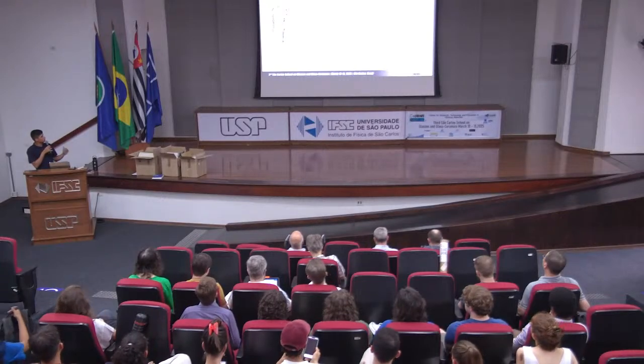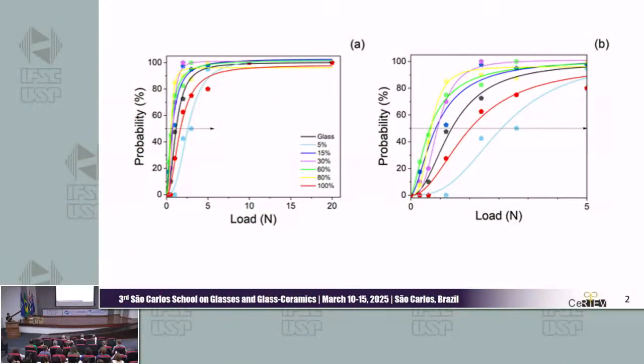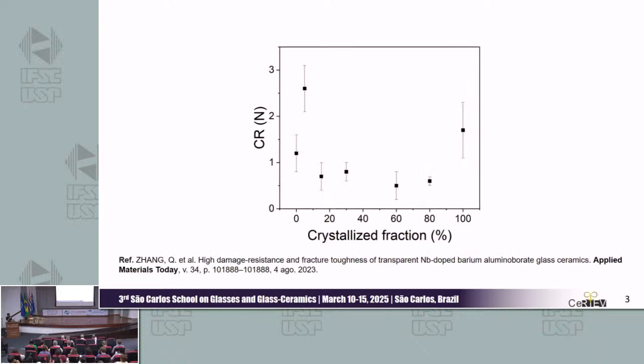In the first graph, we can observe the probability of cracking as a function of applied load for different crystallized fractions. In the second graph, we can observe the increase in the 50% probability, where the crack resistance is measured. There is a relationship between these measured values of CR and the crystallized fraction. We observe a decrease, except in the values of 5 and the only 100%. Thanks.